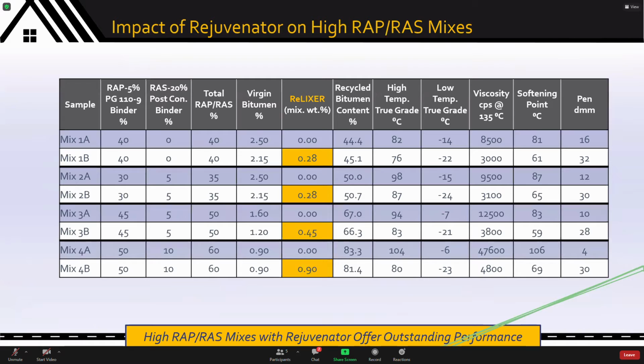So this is a chart that explains what is rejuvenation and what rejuvenators really do. It's a busy chart, so I'll take my time to explain it. Let's take the case of mix 1. In mix 1A, you're using 40% reclaimed asphalt pavement. In mix 1B, you're also using 40% reclaimed asphalt pavement. In mix 1A, there is no rejuvenator, no ReLIXER. In mix 1B, you're adding 0.28% by weight of ReLIXER.